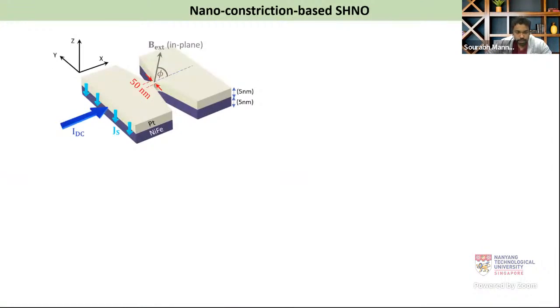So we designed a platinum permalloy bilayer with a 50 nanometer constriction width, and we injected a DC current so that from the platinum metal, due to the spin Hall effect, it can inject a transverse spin current into the adjacent NiFe layer. And now we studied this magnetization dynamics of the auto oscillation using micromagnetic simulation in MuMax.